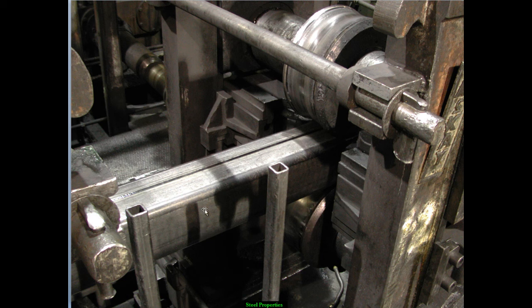One of the things they do is they periodically cut this tubing and take a piece of it and jam it down over a conical ripping device. They put enough pressure on it that they eventually tear the tube. And if they tear the tube at the weld, then they have to discard that tubing because it means the weld doesn't measure up to standards. So it's pretty remarkable what they do.